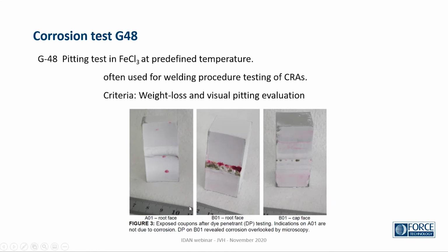If we want to test if our weld has succeeded, we could use a corrosion test. A very popular one is the G48 test, which is using the ferric chloride, which we also saw on the graph earlier for the pitting temperature used to define the pitting resistance equivalent, the PREN value. But here is the test solution we use, and after a certain exposure, you shouldn't see pitting. And we also have a weight: how much could this test reduce the weight of our sample? So there's two parameters. It mustn't reduce the weight too much, and it mustn't cause pitting corrosion like seen in this one.